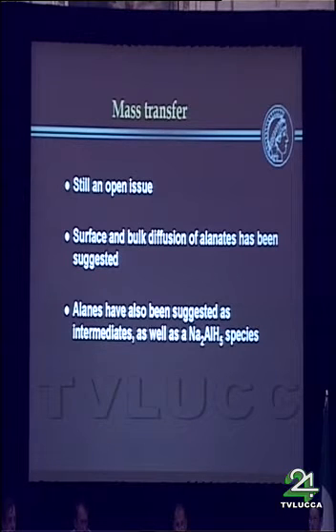Andreas Züttel again has said we have sodium alanate, it decomposes eventually into sodium hydride and aluminum. These grains are hundreds of nanometers in size, and they have to recombine to form a homogeneous compound again. And how that proceeds is still an open issue. Surface and bulk diffusion of the species has been discussed. Alanes have been suggested as intermediates, as well as a disodium aluminum H5 species, but there is so far no experimental proof that these species are really there. And I would say mass transfer is still an open issue for this system.